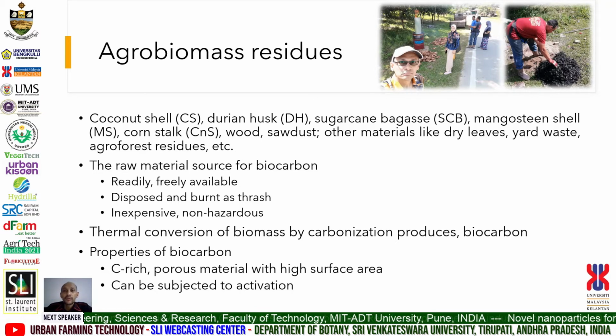This will be our raw material source for biocarbon, obtained through thermal conversion by carbonization using a top-lit updraft carbonization drum. This essentially is a much cleaner process that prevents the release of toxic gases and compounds. Biocarbon is a carbon-rich, porous product with advantageous physico-chemical properties, produced relatively at a lower cost. Activation, if needed, was performed by boiling biocarbon in aqueous salt solution. Use of nitrogen or steam for activation was not required.